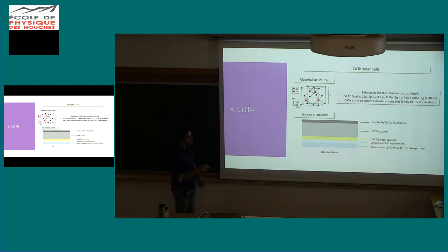It's always the problem that cadmium sulfide and selenide is deposited normally very thin and used to be quite amorphous material, because it's a relatively low temperature that people deposited or need to deposit it. Then you have a lot of pinholes, and one of the reasons is to try to insulate this pinhole. If not, you can shunt your TCO with your absorber. This is one of the main reasons.